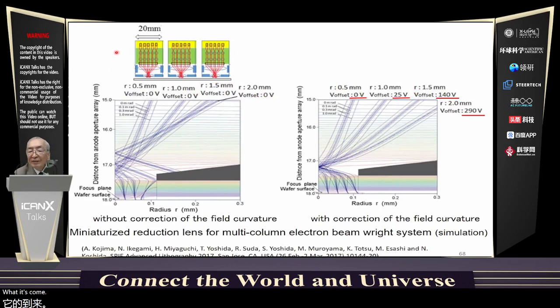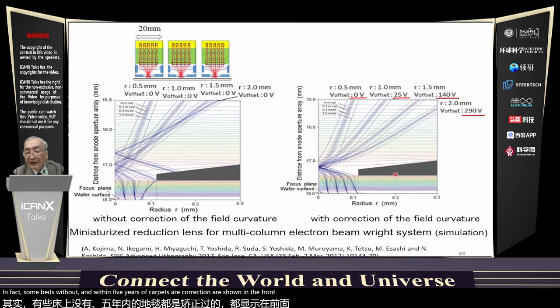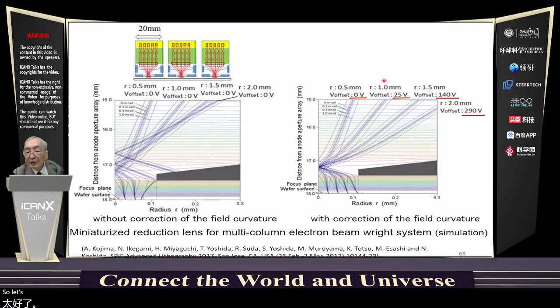Multi-column, as shown in the upper left, is expected for a target commercial electron beam lithography system. Two simulation results of a miniaturized reduction lens, without and with the field curvature correction, are shown in this slide. The right shows that application of offset voltages to the electron emitters is effective for focusing the electron beams on the wafer.